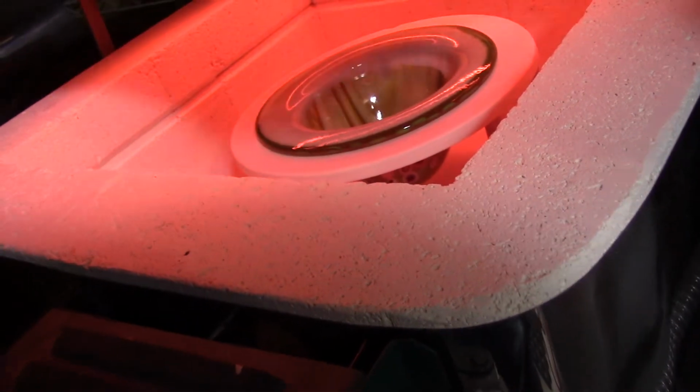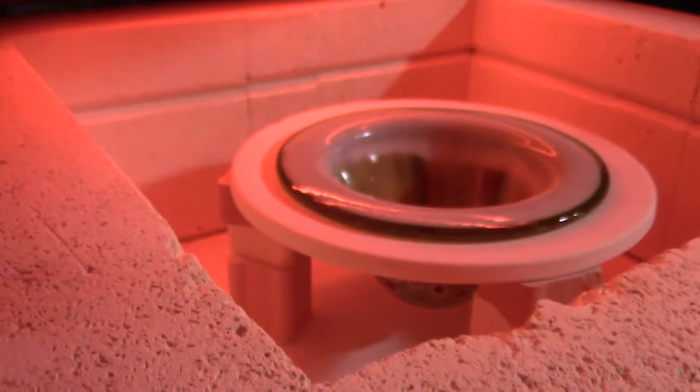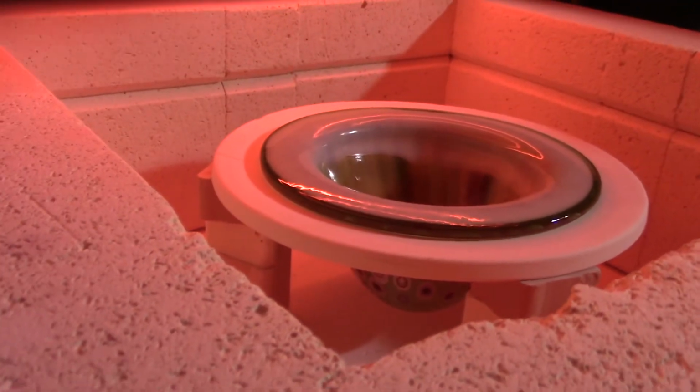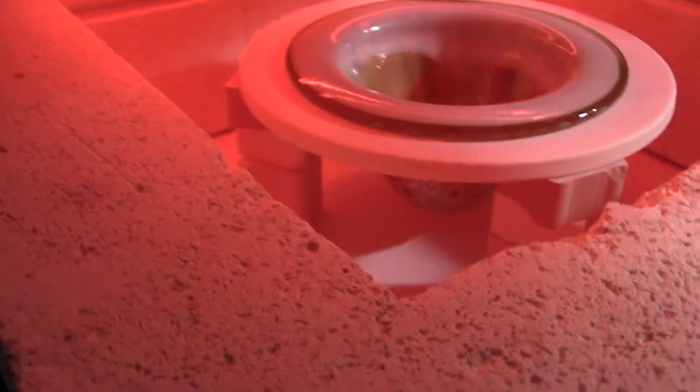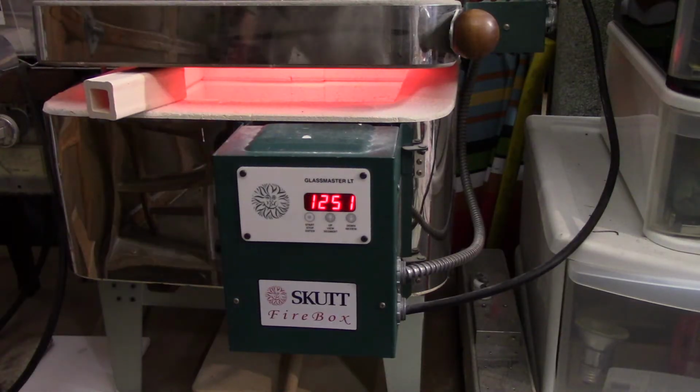Have another person with you and take every precaution. All my kilns are fairly small. You'll see me without gloves here because I had to manipulate the camera and I know what to expect from my kilns. This piece dropped fast, spending only about 10 minutes at 1300 due to the proximity of the top elements. The drop is complete when the vessel contacts the floor and a flat spot forms.